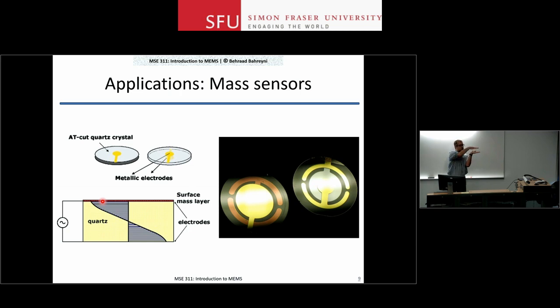So what happens is that you take this device, you make it resonate at its resonance frequency, and now if you have some mass sitting on the top surface, it increases your effective mass. Your stiffness comes from the crystal itself, but the mass can increase because of what accumulates on the surface, and it is very, very sensitive to changes in mass. You can weigh single bacteria using these techniques, and in our lab we've used similar devices to measure less than a nanogram of change in mass on the surface.